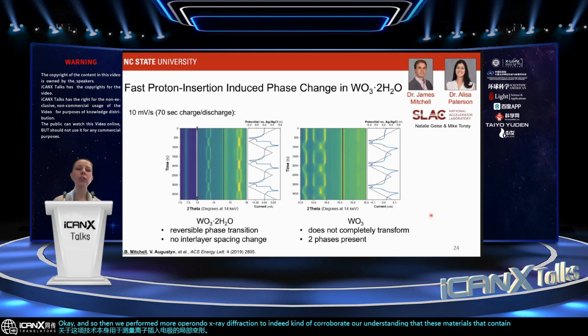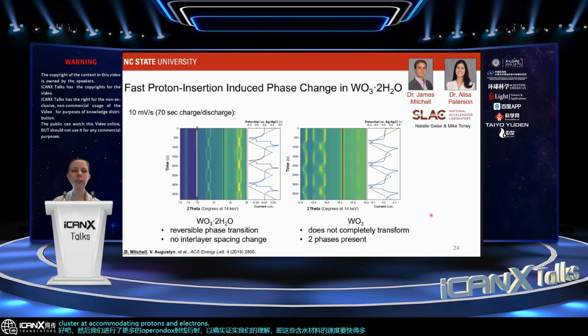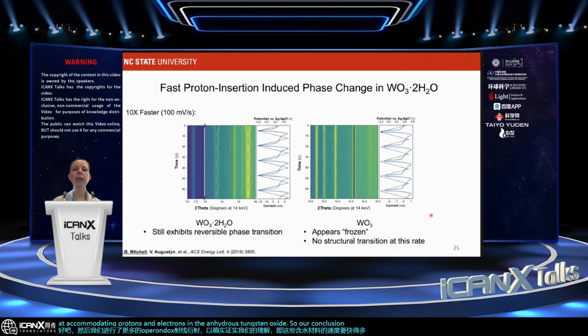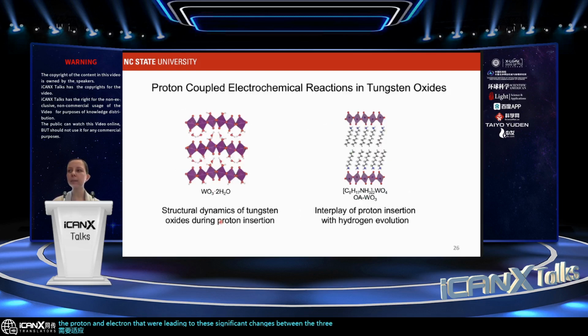Okay, and so then we performed more operando X-ray diffraction to indeed corroborate our understanding that these materials that contained water were just much faster at accommodating protons and electrons than the anhydrous tungsten oxide. So our conclusion was that it wasn't because we were observing a Grotthuss type mechanism or lower activation barriers for desolvation of protons that we observed this fast kinetic behavior in the hydrous material. Rather, it was the kinetics of the structural transitions necessary to accommodate the proton and electron that were leading to these significant changes between the three different tungsten oxides.